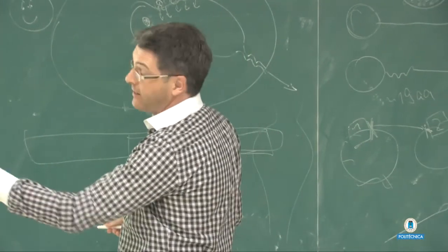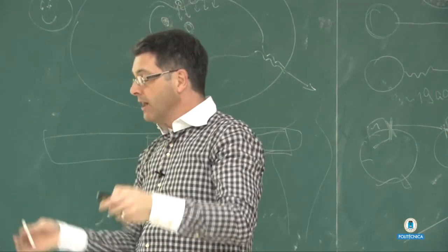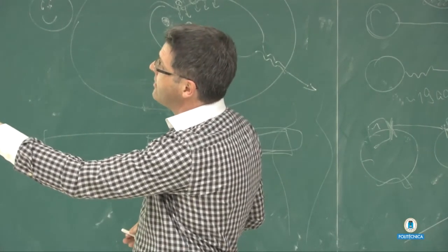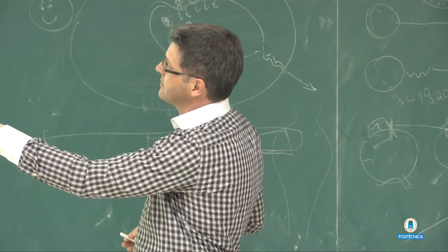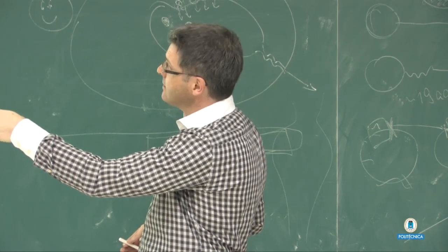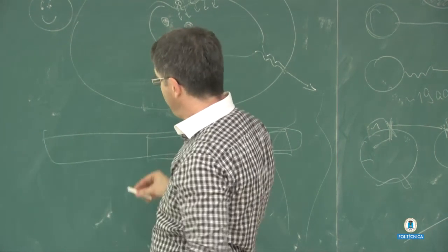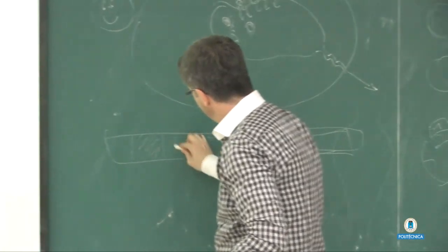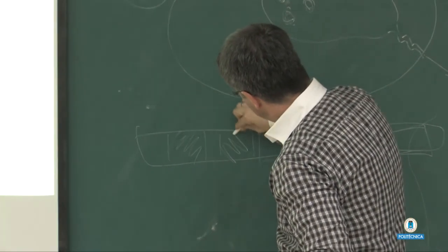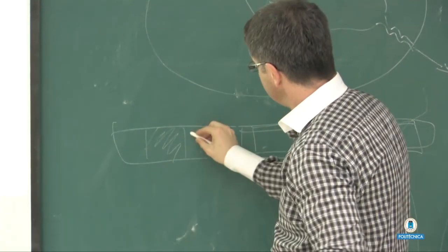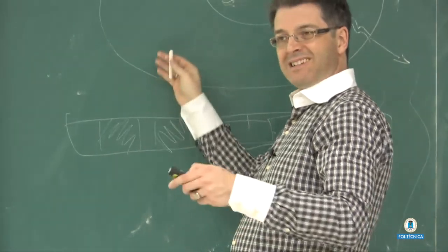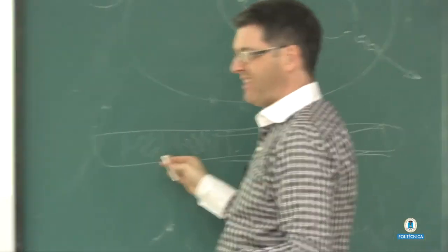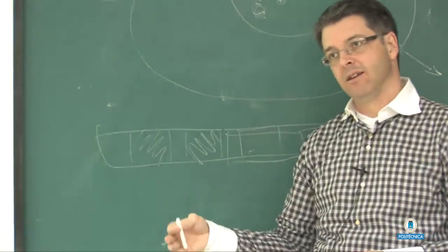And we identified by bioinformatics and modeling that this would be the sequence that is responsible for making the crystals, and this is the sequence for making the matrix. So this would be the crystal, and here would be the matrix, and then a crystal again. But you see there is something in between, and we just left that out and said, well, there is no obvious function for it, remove it.